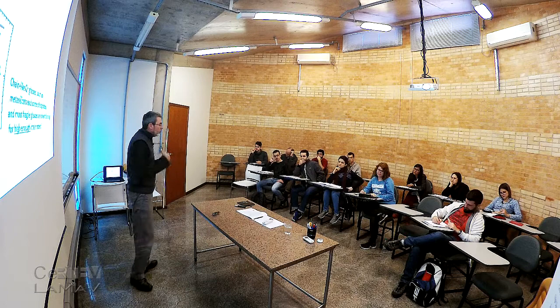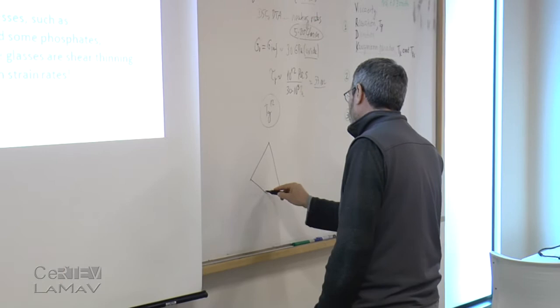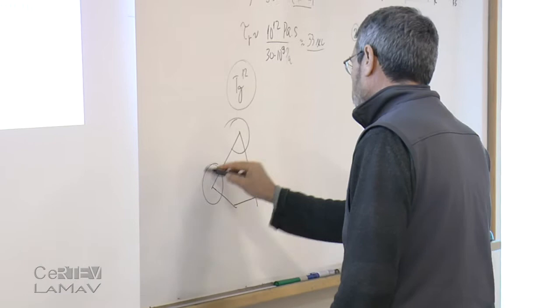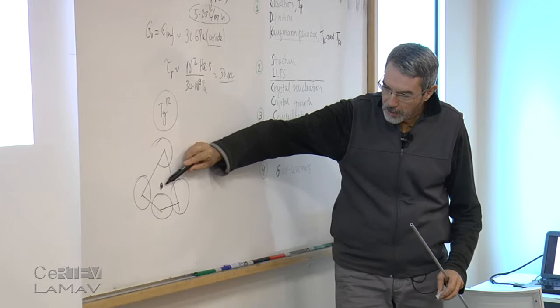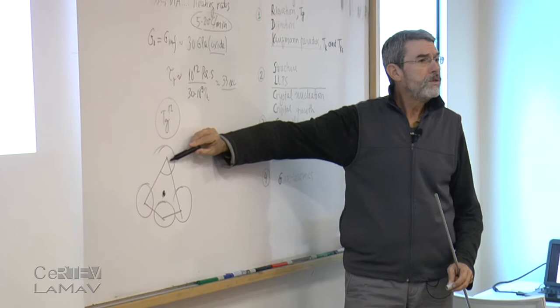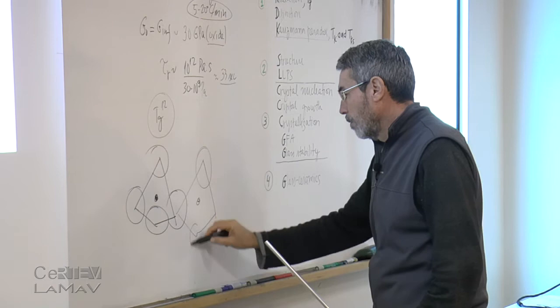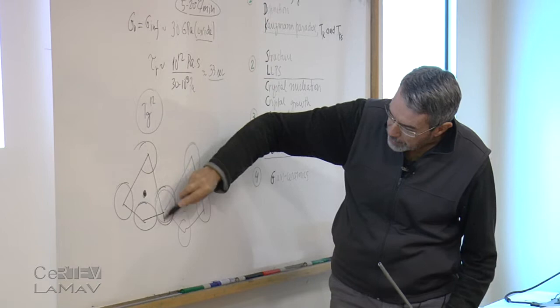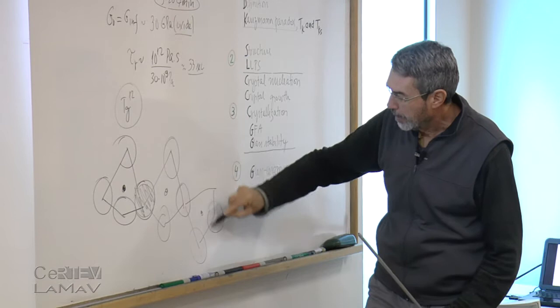By Q2, I'm going to give a class on glass structure, but just for you to know, if we talk about silicate glasses, all silicate glasses, their structure is built of silicon oxygen tetrahedra. Q2 is a notation that says that on average, two corners per tetrahedron are shared. This is called a bridging oxygen. So two corners shared per tetrahedron. This is a Q2 glass.